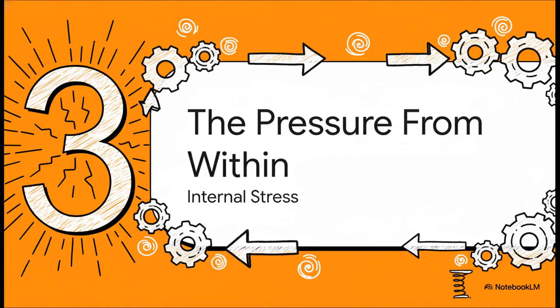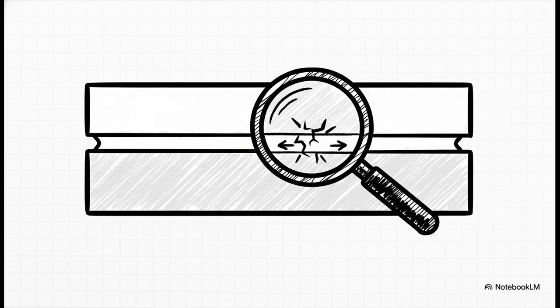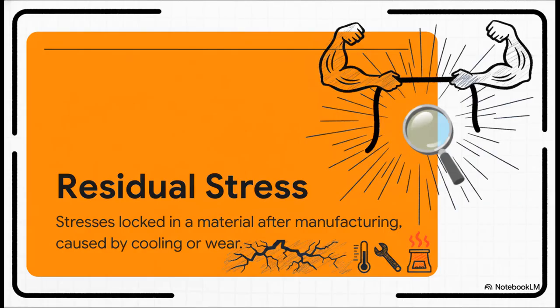Okay, so we've looked at these big external threats, right? Shock, heat. But what if the biggest danger wasn't coming from the outside at all? Turns out, some of the worst failures happen because of pressure building up from the inside. Now, this is where it gets really interesting. You can have the toughest coating in the world, but it can still fail catastrophically because of forces you can't even see, a kind of hidden tension that's been locked inside the material since the day it was made. This hidden enemy has a name: residual stress. The best way to think about it is like a constant, invisible tug of war that's happening deep inside the coating. It gets created when the material is being made, or as it cools down, and it can get worse over time from simple wear and tear. This internal stress makes the coating weak from the inside and vulnerable to cracking.